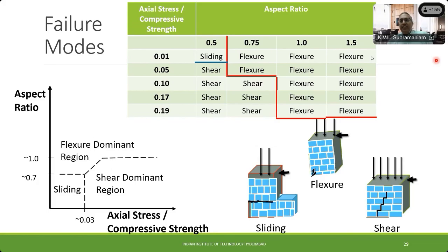So with this now, we were able to establish the modes of failure of masonry walls, which are subjected to different levels of compressive stress. This should be levels of compressive stress, not compressive strength. So if a masonry wall is subjected to a low compressive stress, this 0.01 refers to the value as a percentage or as a fraction of the compressive strength of the wall itself. So we went from something like 1% of the compressive strength of the wall to a compressive stress in the wall, which is almost 20% of the compressive strength.